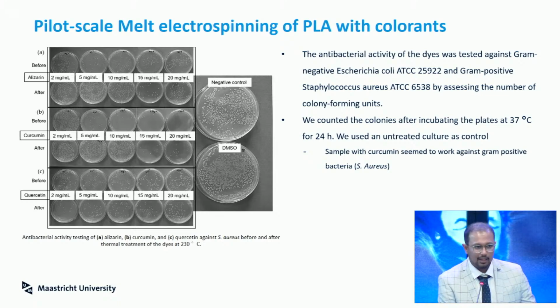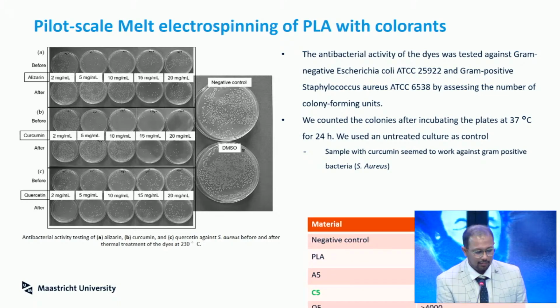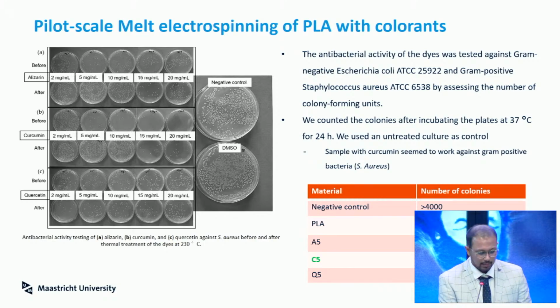And then we did the same test against the same bacteria with the samples that I made, with the non-woven sheets that we had. If we count the number of colonies, the dots are the number of bacterial colonies that we have. If you look at these colonies, we could see that in terms of pure PLA and the other colorants, we didn't really have any kind of antibacterial effect, but with curcumin, we did have it. And as you can see on the picture on the left side, among the other colorants tested, curcumin was also the most promising candidate. So it was quite a positive outcome that we were hoping for when we did these trials.